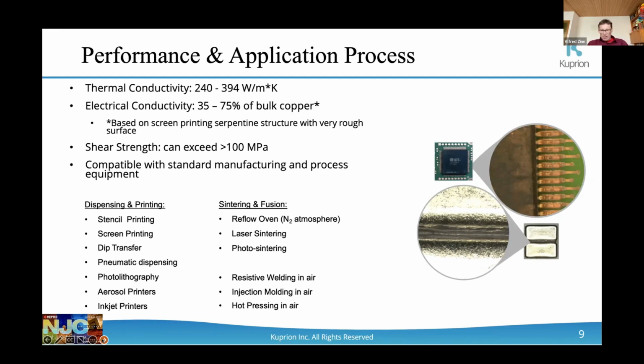Then we have other products I mentioned for these, CTE adjusted heat sinks and thermal ground planes. That's a different formulation. And we do a lot more things. We do thermal vias that we can fill. We do this in through glass vias, for example, very small, different formulation, obviously. Again, the key there is to adjust the CTE so that it matches the glass and you don't get into issues with materials compatibility. Does that answer the question?